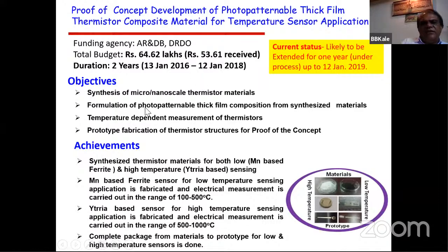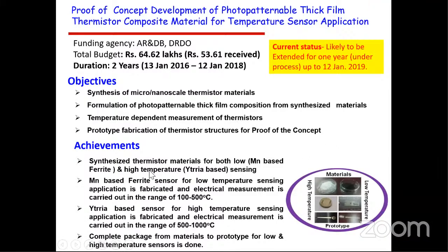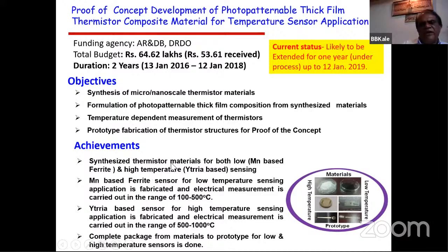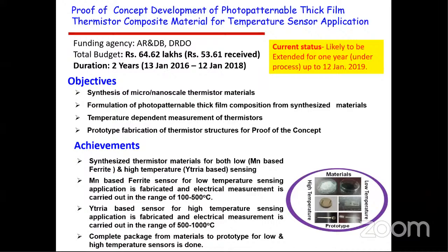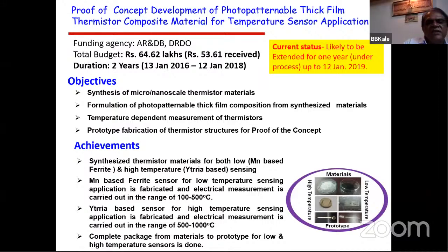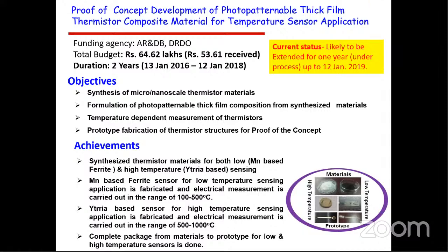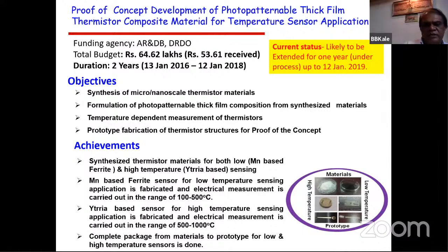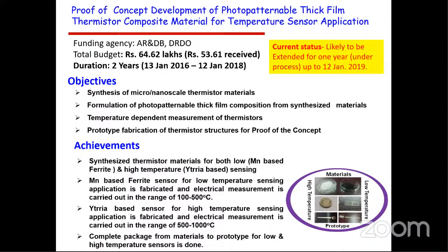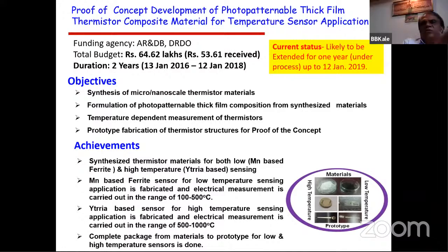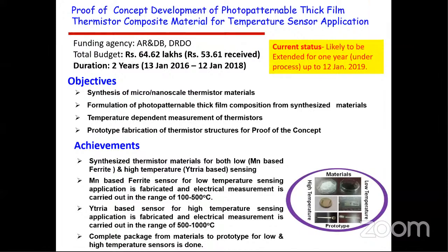This is a temperature sensor. This is based on ferrite-based material, manganese-based ferrite. We developed the composition for 500 degrees Celsius and 1000 degrees Celsius. So one sensor can go up to 500 degrees centigrade with sensitivity of 0.1 degree, and 1000 also 0.1 degree, something like that. This is basically for DRDO, because they have turbines. One turbine goes to very low temperature, and another turbine goes to very high temperature, up to 1000 degrees centigrade. So both the sensors we developed for DRDO.